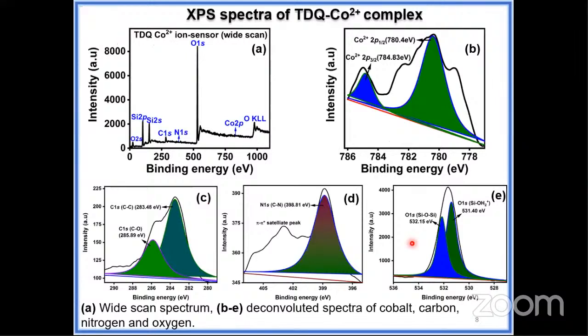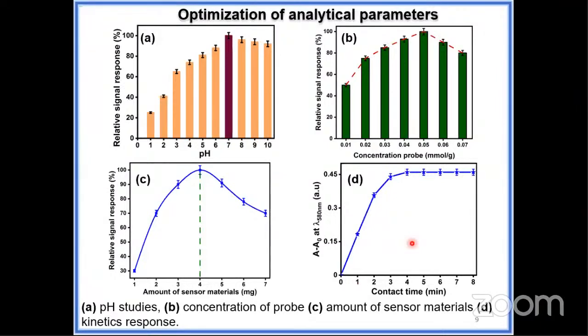After that, we prepared the cobalt complex to know the oxidation state of cobalt. It confirms that it is in the cobalt 2+ oxidation state. Also, we have confirmed all the elements present in the material. After confirming all the material characterization, we also optimized the analytical parameters to develop a cobalt sensor. In pH studies, the material shows the highest intensity signal response at pH 7 with a probe concentration of 0.05 millimole with 4 milligrams of material.